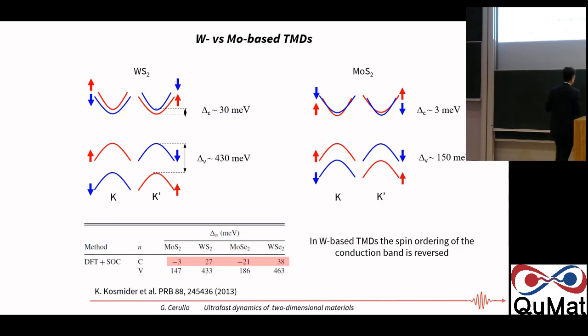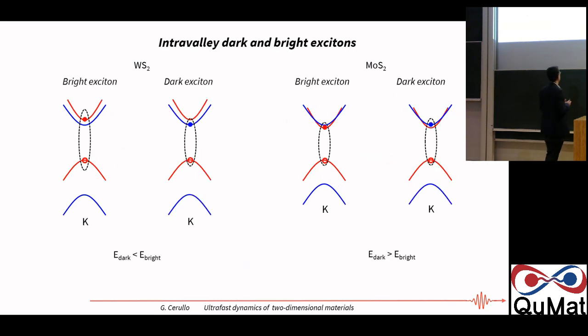So here you have what is called the dark exciton. You have a state which is at lower energy, which is dark, which you cannot access because you need a spin flip. So how can you see this dark exciton? This is acting like a sink. So once you create the bright exciton, it goes to the dark exciton. So in fact, in WS2, the dark exciton has lower energy than the bright exciton, while in MoS2 it has higher energy.